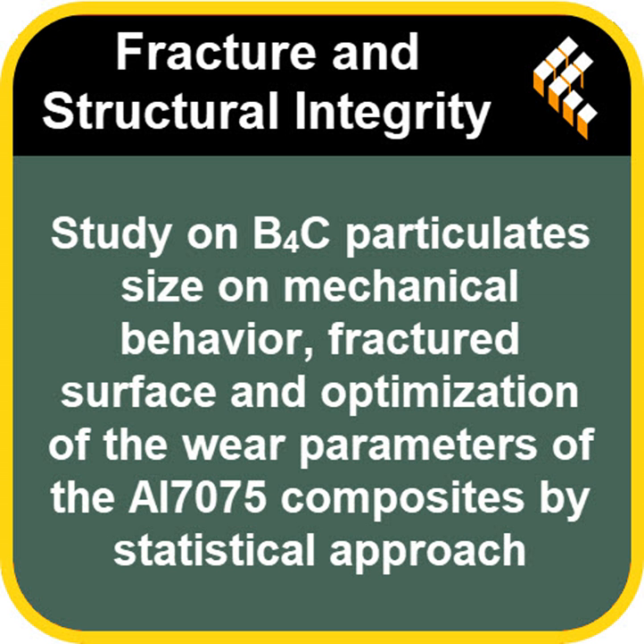Okay, let's talk about the surface itself. What did the microscope show after all this rubbing and testing? Starting with surface roughness, how smooth or rough was it? Well, again, nano came out on top for smoothness. The nano-sized particles tended to reduce the surface roughness both before and after wear testing. Why smoother with nano? They fill in the microscopic gaps more effectively, as we discussed with porosity. And because they're harder and smaller, they resist being deformed or pulled out during polishing or wear, leading to a smoother finish.